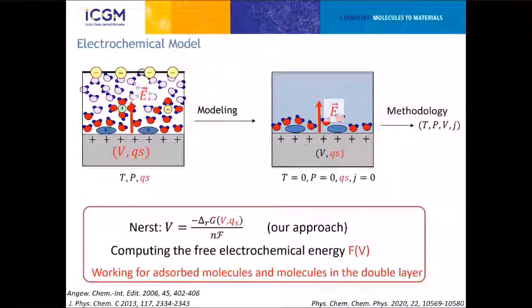So what you need is more complex modeling that should include the surface charge, of course the electric field, and eventually explicit and implicit solvation of your interface. In this case, you get some kind of equivalent Nernst equation that will depend on the local electric field. That is not practical, so to be practical, we are using the free electrochemical energy. That will be our main energetics. And it works both for adding some molecule on the surface, but also for molecules in the double layer. So it allows investigating a wide range of very different behaviors in electrochemistry, and answering questions about reactions happening on the surface or in the double layer.